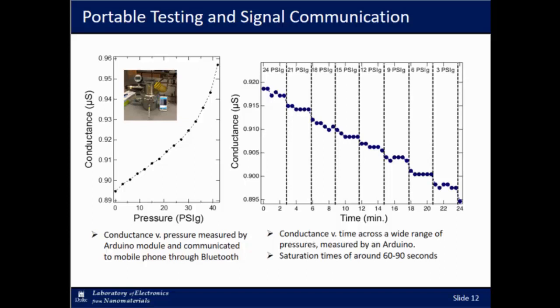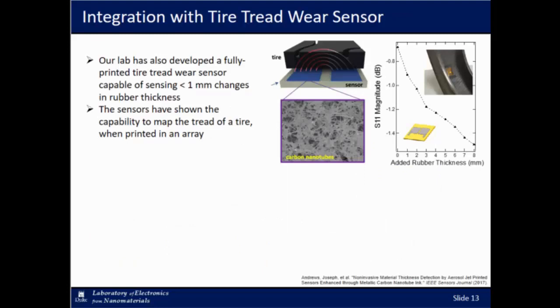So our lab has also done a lot of work developing a material thickness sensor that we plan to use as a tread depth sensor in tires. This was some work that we published over the summer. And basically, this is another fully printed device. It's 2 printed electrodes that are printed adjacently, and an electric field is applied between those electrodes. A lot of that electric field is lost directly between the electrodes, but some of it extends out of plane and is perturbed by the overlying material. And that perturbation depends on that material's thickness, and we can use that to actually back out the added rubber thickness. So this sensor is placed underneath a tire, and rubber plies are added, and we see a fairly linear change in the signal reflectance between those two electrodes.